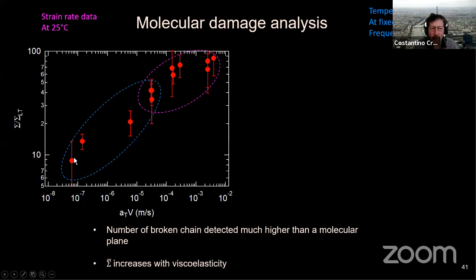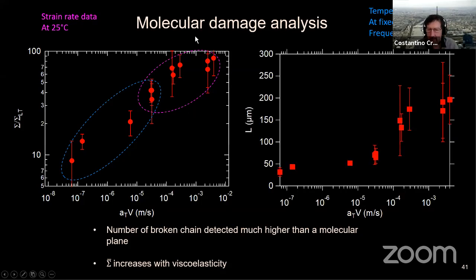Now, just note that indeed, the damage increases with roughly a power law as a function of ATV. The blue here is the temperature data. The purple is the strain rate data. Now, if you look at the distance, we were not going to do anything with that, but it gives you an idea. It goes from about 30 micron to 200 micron.